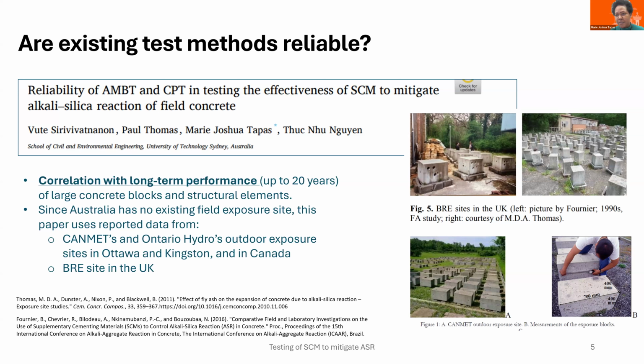So this paper was published about 2 years ago, where we looked at long-term data over 20 years, actually now over 30 years already from recent updates. Long-term data of ASR concrete samples in the UK and in Canada. Unfortunately, we don't have a field exposure site in Australia. And probably that's because we don't have as bad a case here as what we have in other parts of the world. But nevertheless, this data are very valuable and the only data we could actually use to benchmark.